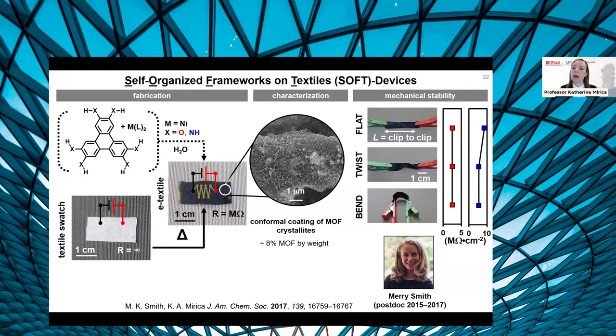We can bend these, we can twist them, we can flatten them out, and their conductivity is not significantly perturbed by those mechanical perturbations. And we believe that to be due to the fact that we're well above the percolation threshold of charge through this composite material due to very tight packing of the metal organic framework crystallites on the textile substrate.